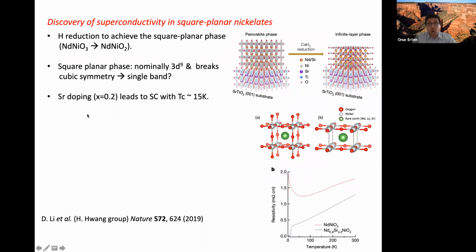And when they doped it with strontium, so this is the parent compound without any strontium doping, it is more like a metal, but the resistivity picks up at low temperatures, probably due to disorder. But when you dope it with strontium, the resistivity drops to 0, becoming a superconductor at about 15 Kelvin. So this is the first discovery of superconductivity in nickelates.